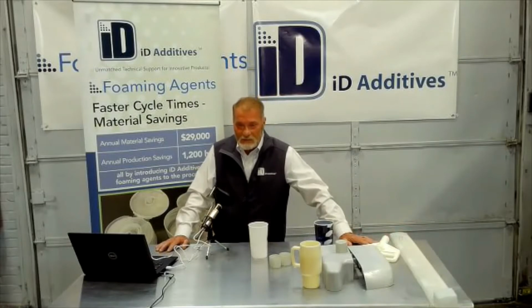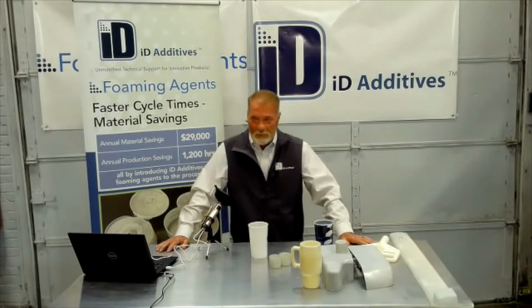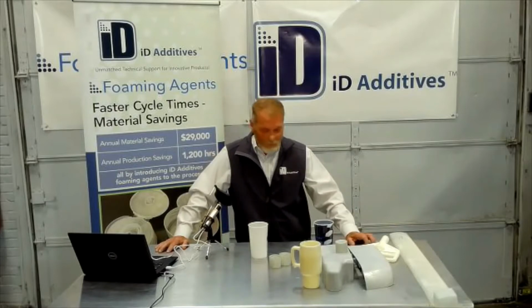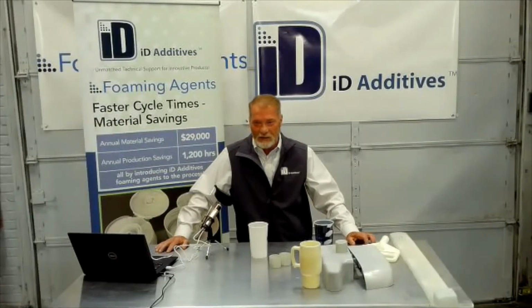Go ahead. We have another question. Do we need to adjust foaming agent concentration based on regrind percent? No. When you're running regrind, if you're running 1% foam, you stay with 1% foam. If you're running regrind that's foamed, you still stay with 1% because you're going to lose a lot of gas out the rear.